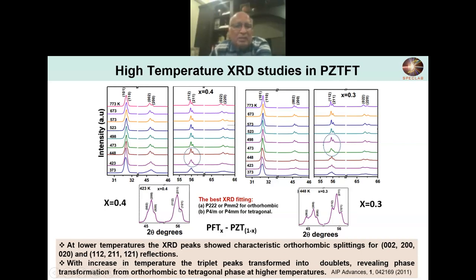These three peaks are 112, 211, and 121, and here it is 020, 002, and 200. So all three peaks are here and here. These three peaks are associated because the structure in this temperature region is orthorhombic. As you heat the sample up above the temperature, they become a doublet, and that's the tetragonal phase. So we saw a definite proof of a structural phase transition in this material at a certain temperature.